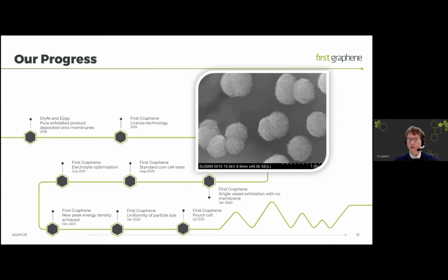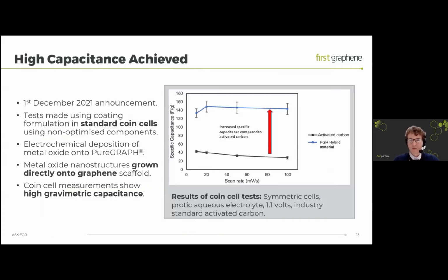And then we've also started to move on in mid 2021 to electrolyte optimization. So we know that this system needs to be optimized, and the electrolyte needs to be optimized in tandem with the material. So that's what we've started to do. And then we announced a new peak energy density at the end of 2021. So if I'll just move on to the next slide.